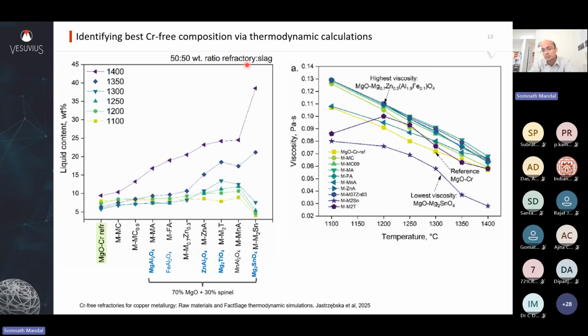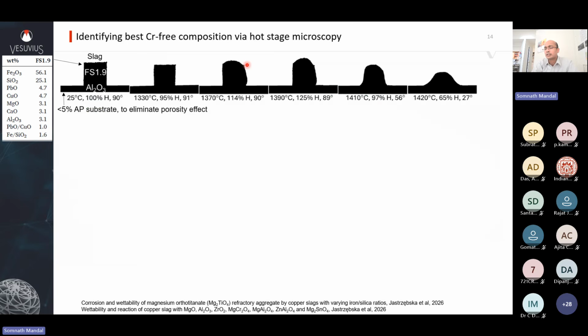And this is also done by some research groups. This is a very expensive method to do viscosity, so there are very few papers in general. And also you need to worry about your platinum reacting with your slag, because some of them contain elements that are not compatible with platinum. So there is a little bit of challenge here. So that's how you can get the viscosity measurements from your material.